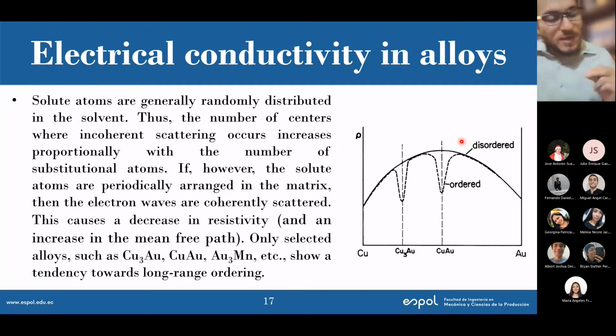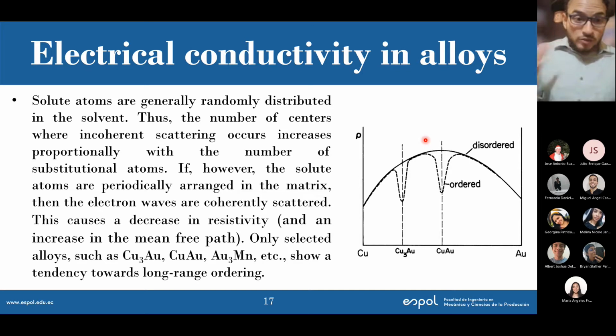And if I see, just looking at the graph, I see a difference between alloys, in this case a copper gold alloy, where I have a random distribution and where I have a specific order of atoms. If I have a random distribution, the number of centers where incoherent scattering occurs increases proportional with the number of substitutional atoms. And that makes sense.